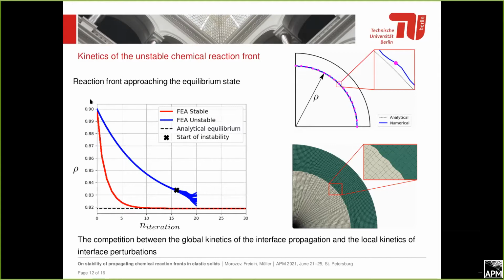However, if we consider an unstable configuration, for a certain amount of time our circular interface propagates as circular, but at some point these perturbations start to be visible. And this corresponds perfectly to what we have obtained in our analytical solution. So the velocity of amplitude growth starts to be dominant in this ratio of velocity with respect to the global kinetics of the chemical reaction front.